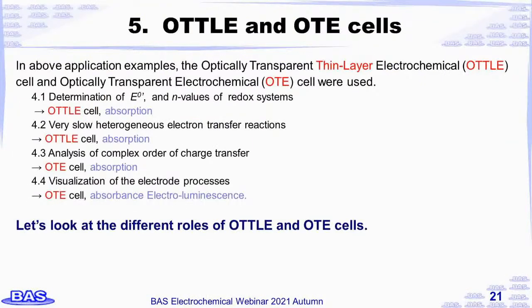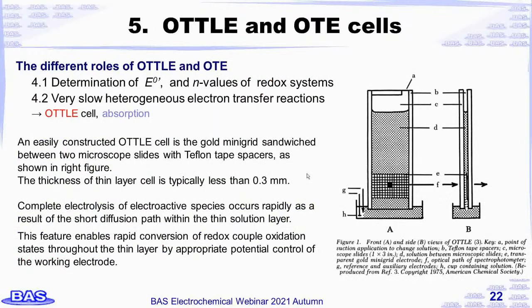In the above application examples, the optical transparent thin layer electrochemical OTTLE cell and the optical transparent electrochemical OTE cell were used. Then let's look at the different roles of these two types of cells. The first and second examples used OTTLE cells. An easily constructed OTTLE is a gold mini-grid sandwiched between two microscope slides with Teflon tape spacers, as shown in the right figure. The thickness of the thin layer cell is typically less than 0.3 mm.